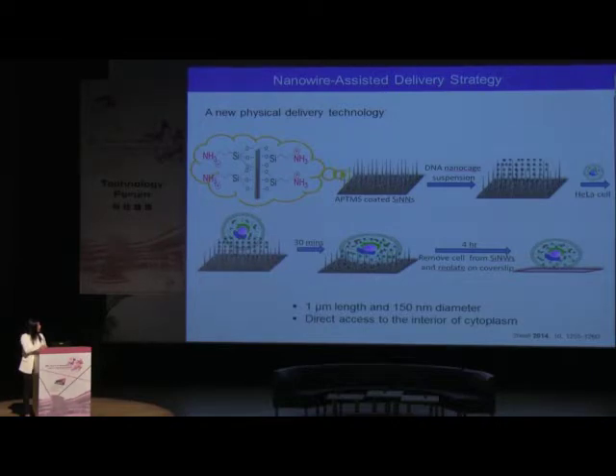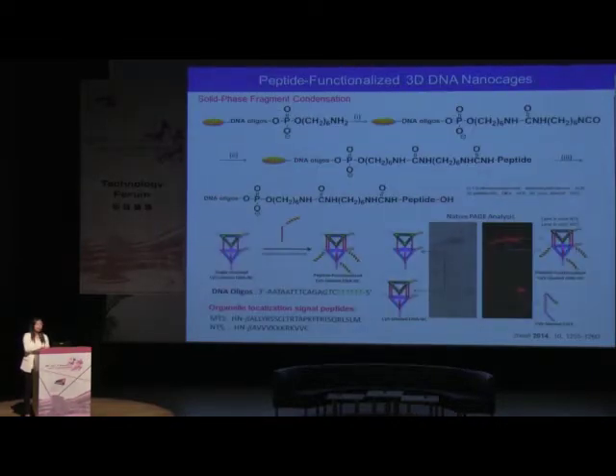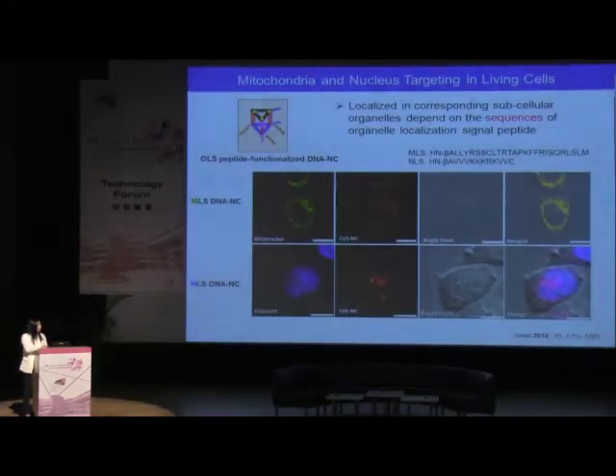And at the same time, we have this delivery approach, and we also have to modify our DNA sample here, taking a DNA cage with some organelle localization signaling peptides using the typical solid phase fragment condensation reaction. Once we have this DNA cage carrying two specific peptide sequences, we just try to put them into the cell. And basically, we found that depending on the sequence we put on the DNA cages, the DNA cages can be successfully localized in different subcellular environments, for example, in the mitochondria or in the nucleus.